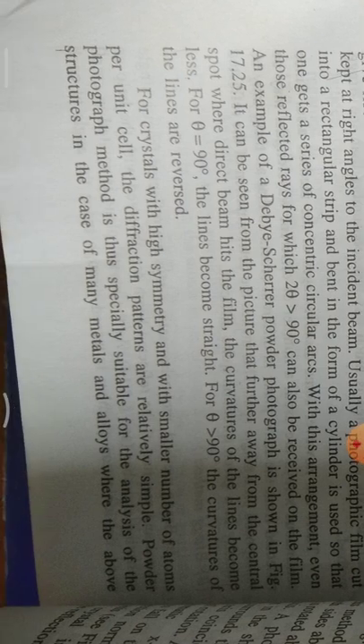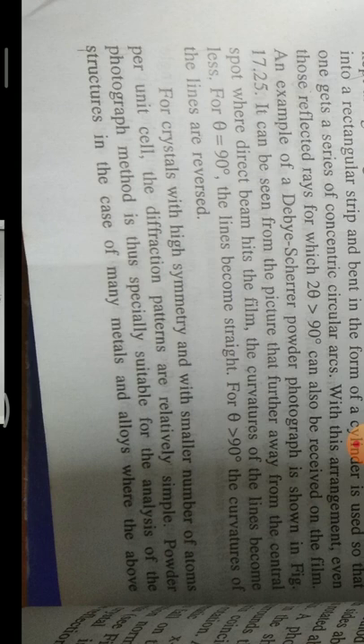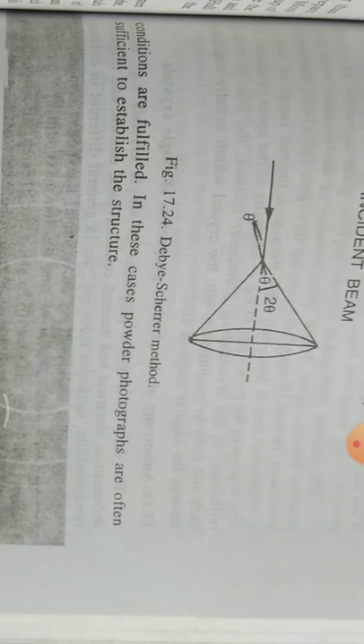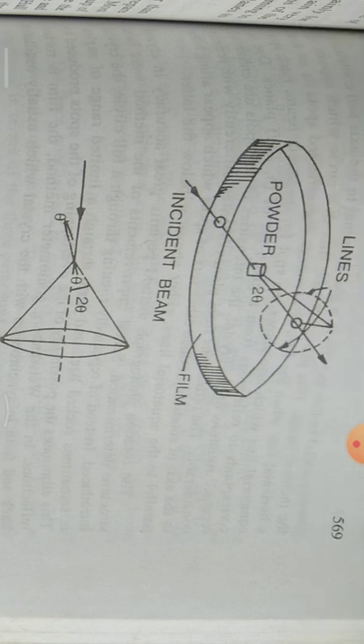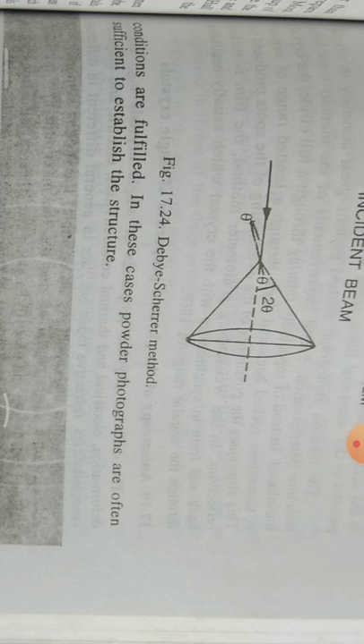For crystals with high symmetry and with a smaller number of atoms per unit cell, the diffraction patterns are relatively simple. The powder photograph method is thus especially suitable for the analysis of structures in the case of many metals and alloys where the above conditions are fulfilled. In these cases, powder photographs are often sufficient to establish the structure. This is diagram 17.24, showing 2θ, the powder, the lines, the incident beam and the film.